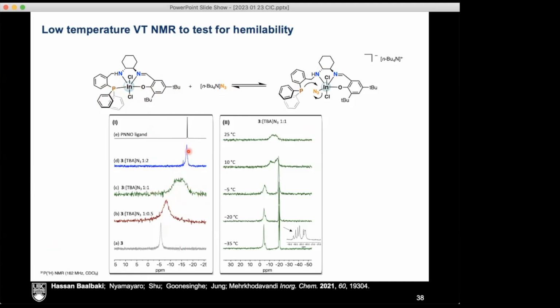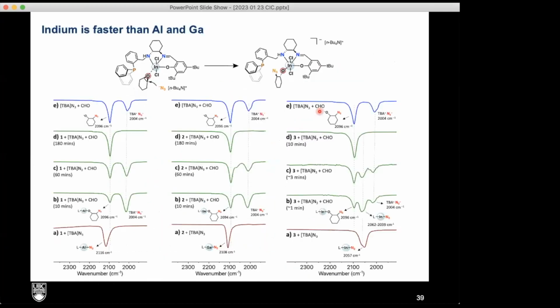So here we have two equivalents of azide. It's absolutely off. Here we have half an equivalent that's clearly in between. And this here is 1-to-1 azide. And when we look at what this broad mixture of things is, there's definitely something going on here where the azide is coming off and on and forming various different species. We then wanted to compare this process and the reactivity here of the azide attacking the epoxide for all three metals. So this is aluminum, this is gallium, and this is indium. And for all three, the same thing is happening. The epoxide is coordinating, the azide is attacking, forming this new species.